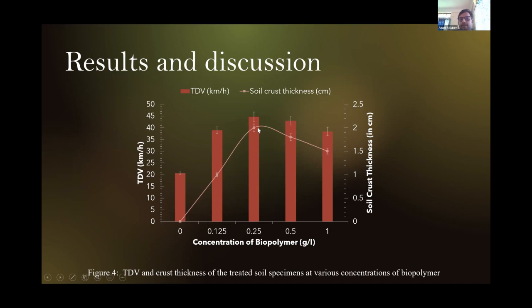Then we found the optimum crust thickness as well as threshold detachment velocity at 0.25 gram per liter concentration. And after that, the crust thickness decreased. It was mostly because when we mix xanthan gum with water, it becomes viscous. So after a certain concentration, the permeation of these xanthan gum sprays into the soil becomes difficult.